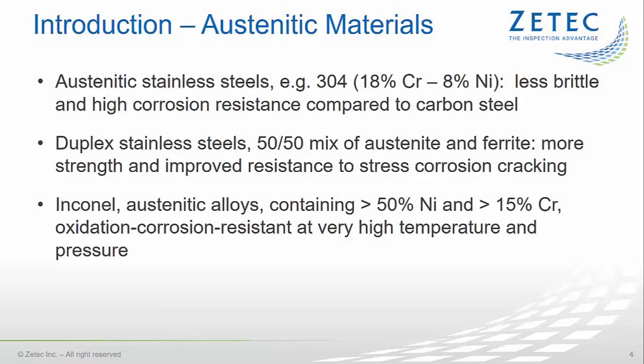Let's have a look at some austenitic materials that are typically used in pressure retaining welds. Austenitic stainless steels contain a minimum of 16% chromium and sufficient nickel and/or manganese to retain an austenitic structure at all temperatures from the cryogenic region to the melting point of the alloy. They have an austenitic crystalline structure, which is a face-centered cubic structure. This makes the steel less brittle at low temperatures and essentially non-magnetic.